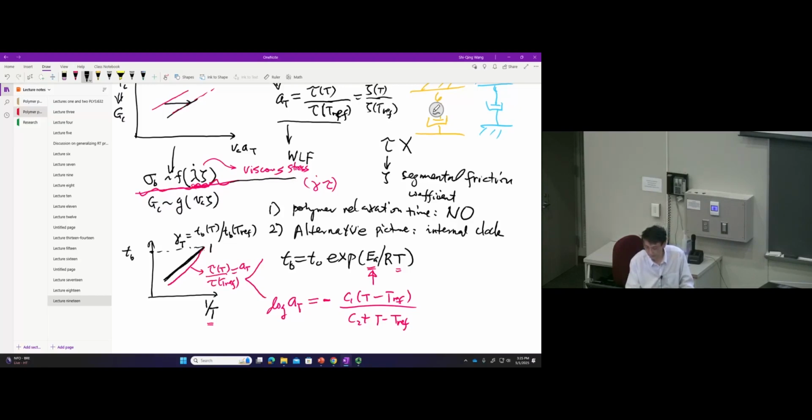So relative to this low temperature, normalizing the reference temperature. In other words, the reference temperature is this lowest one. Then you get a factor of gamma versus aT, and they are not identical. They can be quite similar. So a lot of current research in our group is to delineate the difference between them.